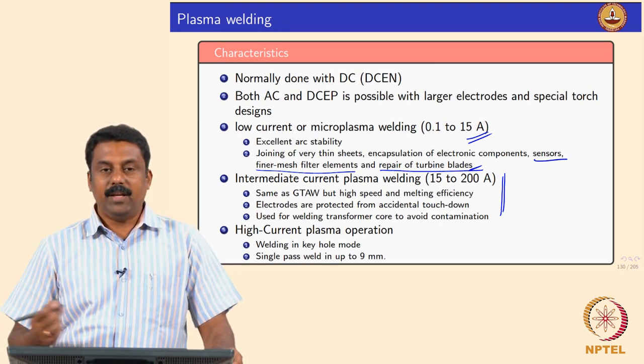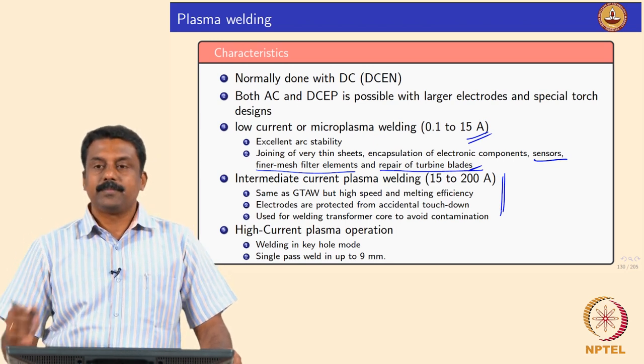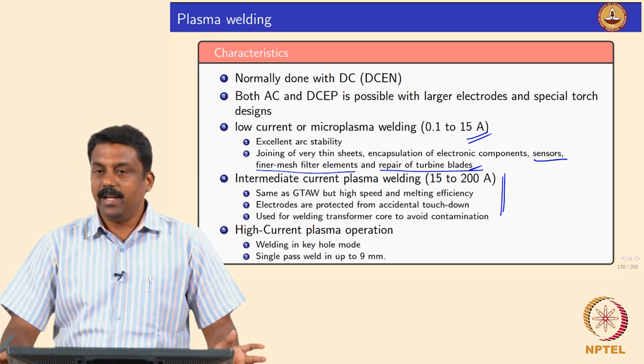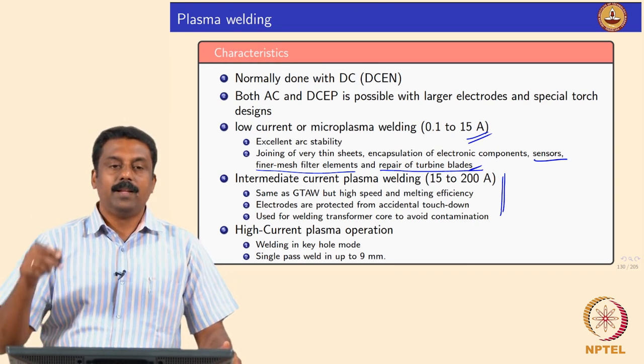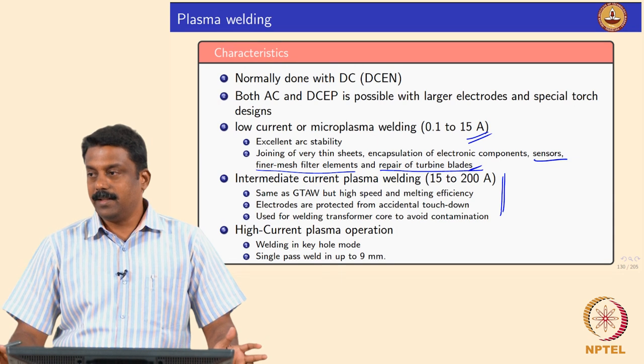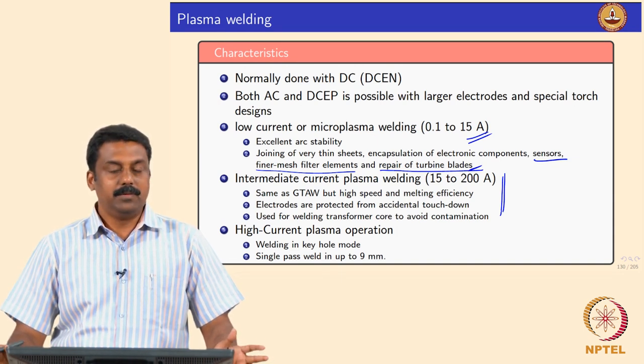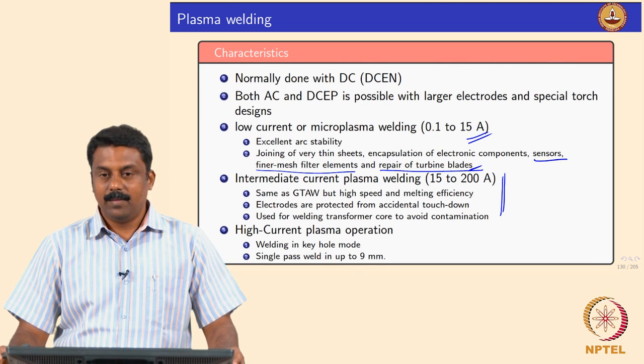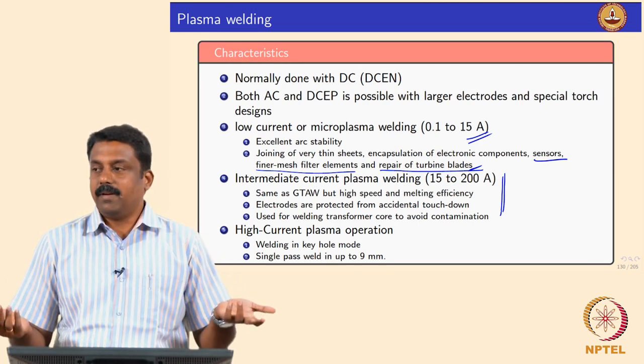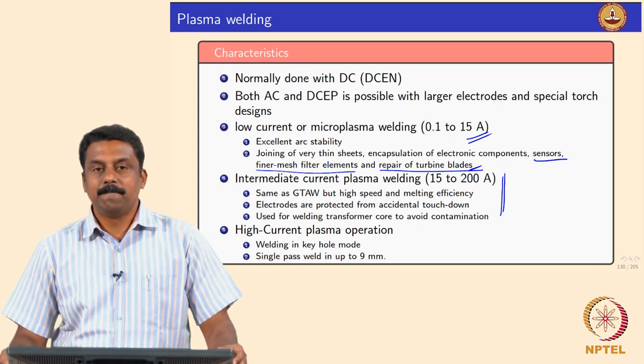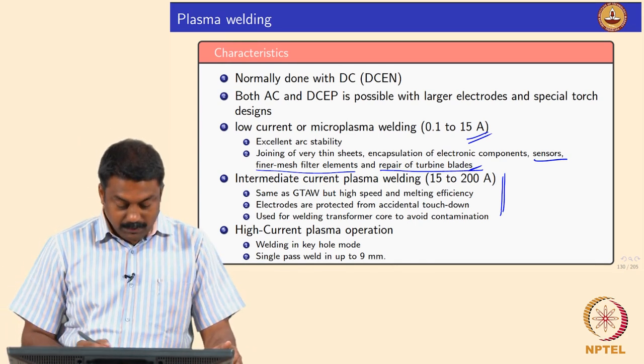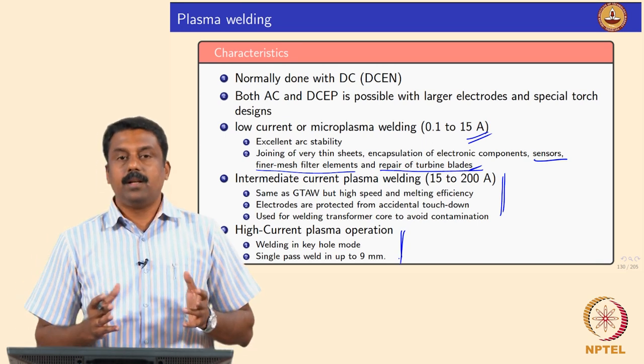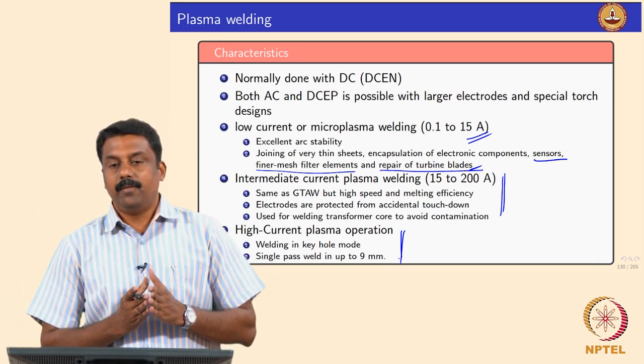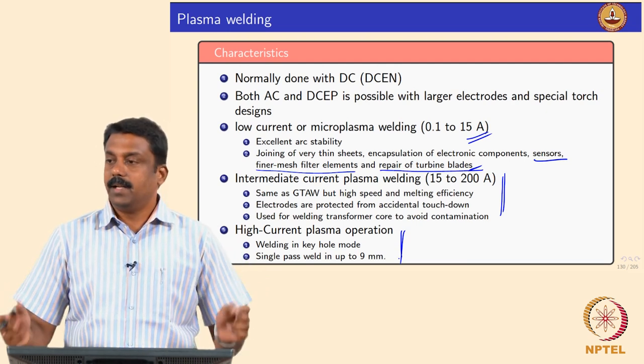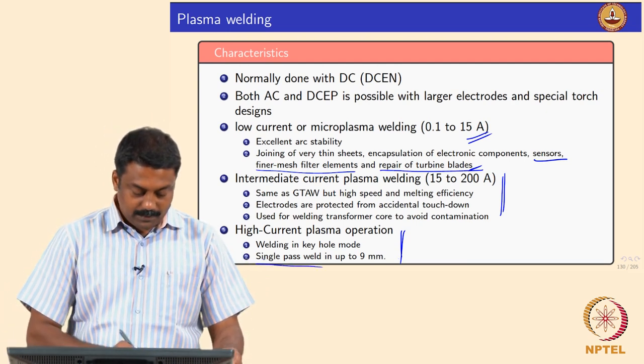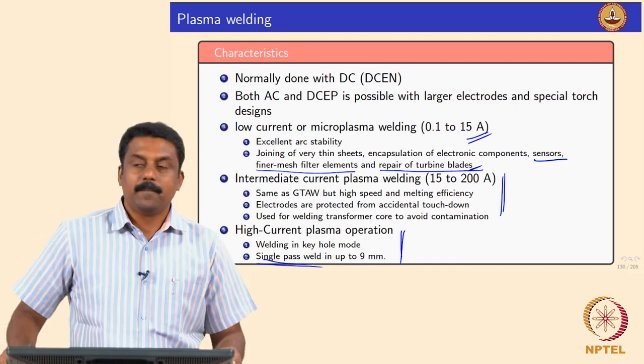Okay, and in this process, another advantage is arc ignition. Sometimes when you are doing a short circuiting ignition, if the electrode touches down you have a problem, because then the tungsten can have short circuiting leading to tungsten inclusions. In this case, you always strike an arc in a non-transferred mode first, so the arc is always on. Isn't it? Okay. And you can also do it in high current mode, then you generate an enormous arc energy density, the beam, and we could get a penetration as high as 9 mm in steel. In a single pass, we can weld. Right? Okay, good.